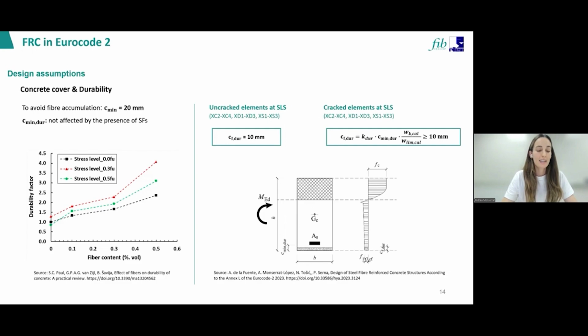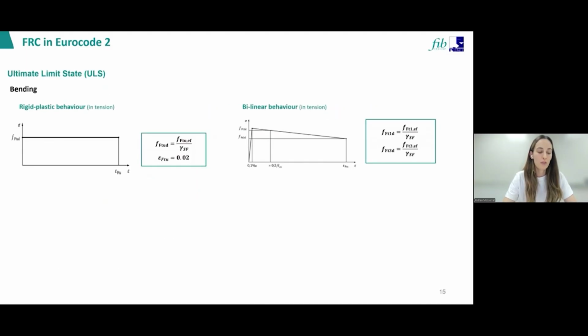Since steel fibers close to the exposed surface may be subjected to corrosion and may potentially lead to rust staining effects, for this reason, Annex L introduces an additional consideration based on the concept of sacrificial layers, where the tensile contribution of fibers close to the surface is disregarded in the structural verification. Well, once the material assumptions are defined, Annex L provides a specific provision for both ultimate and serviceability limit state.